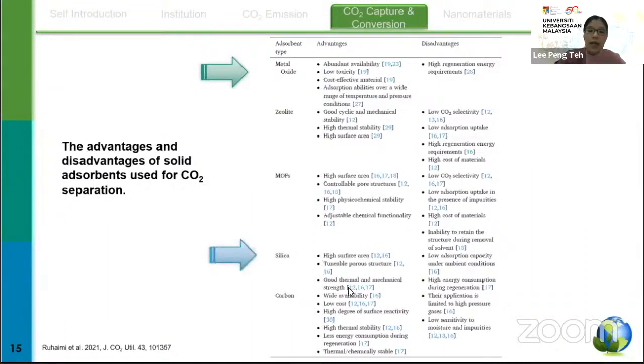We also have silica material, silica-based adsorbents. It has high surface areas, tunable porous structures, and good thermal and mechanical strength. It should be highlighted that the high CO2 adsorption performance is related to the adsorbent's physical and chemical properties. And the physical and chemical properties basically depend on the modification approach used as well as during the synthesis phase.